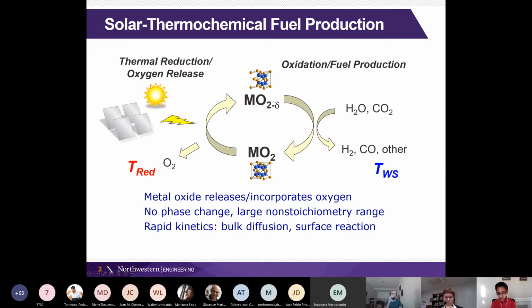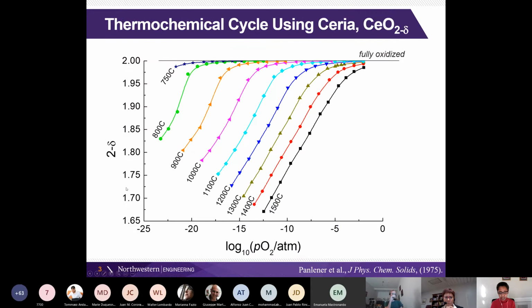But that means that we want a material that's going to undergo a large non-stoichiometric change with this change in atmosphere. Turns out that ceria is an excellent benchmark material for this. So I'll be describing to you how we understand ceria, but also some of the lessons learned will be applied to other materials. And it's an ideal material because the thermodynamics have been very well studied. So we know exactly how the oxygen content in the material changes as a function of oxygen partial pressure and as a function of temperature. So this is data from 1975, very clean data. And how we use this is the following.